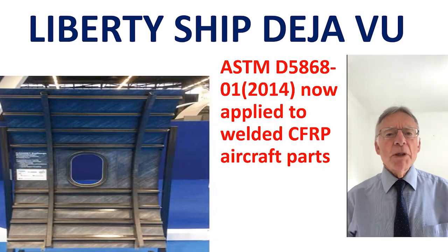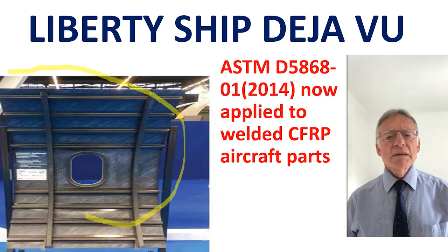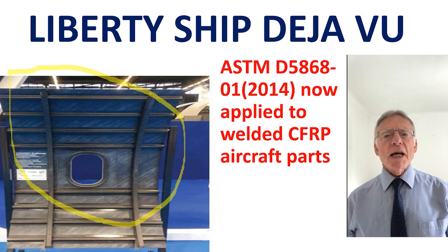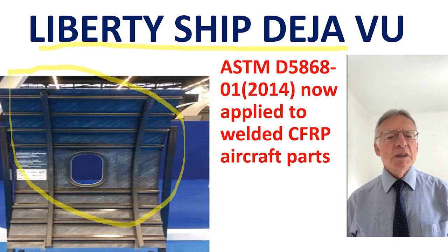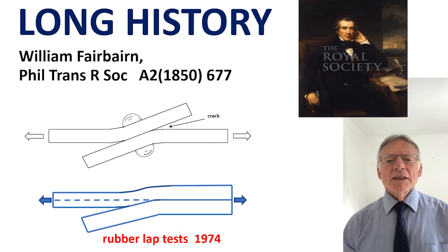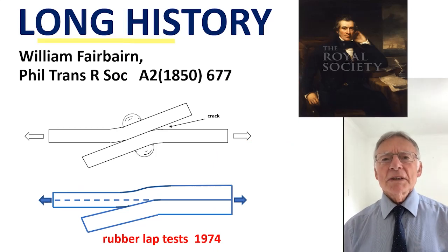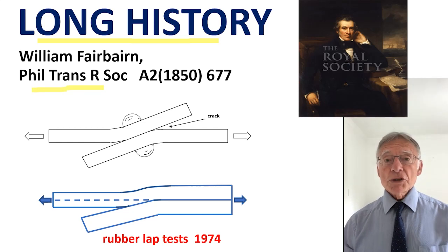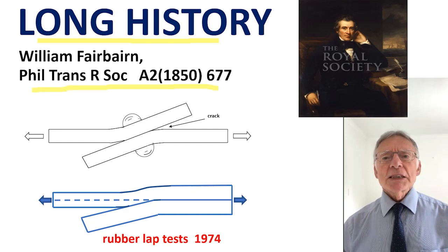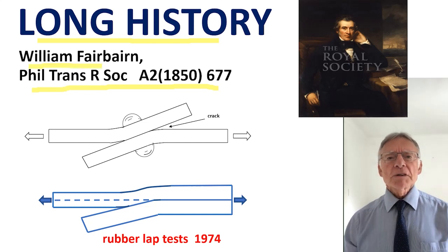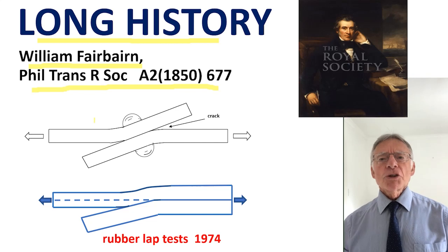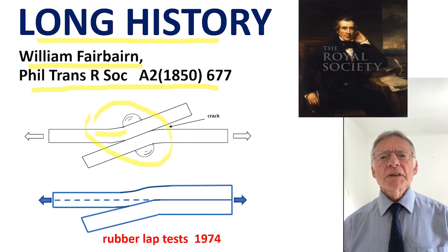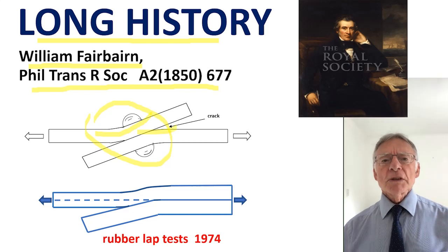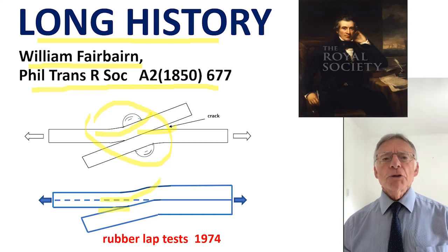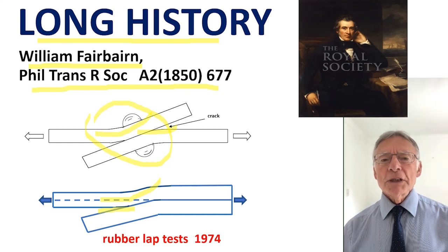Now that carbon fibre aircraft parts are being made by welding carbon fibre sheets, there's a danger that cracks can run through the welds at low energy, with disastrous effect. Another Liberty ship disaster may follow this ASTM standard. There's a long history behind this lap joint crack test. Originally, it was described in Phil Trans during 1850 to understand how riveted iron railway bridges failed. William Fairbairn proved that the joint deformed like this by bending, then cracking the rivet. In 1974, I showed with rubber strips that the joint does bend slightly and a low angle peel crack goes through the lap joint. It's definitely not shearing.